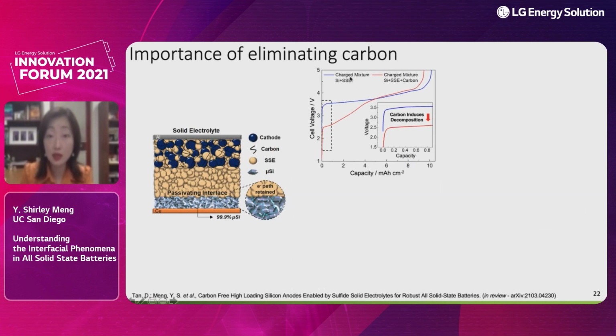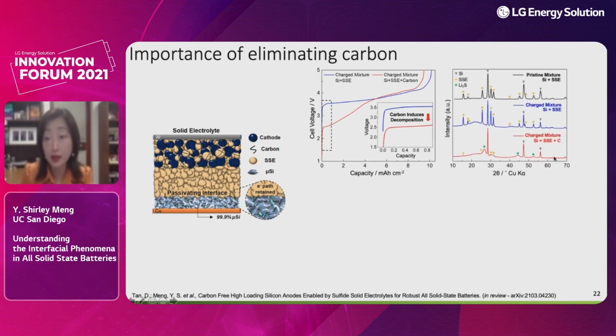So this is where you have carbon. If you add carbon into the silicon, your voltage curve will look different. What happens is that the solid electrolyte I mentioned on the anode side, when the voltage goes very negative, generates Li2S or lithium sulfide. In this particular case, we clearly detect the lithium sulfide here.